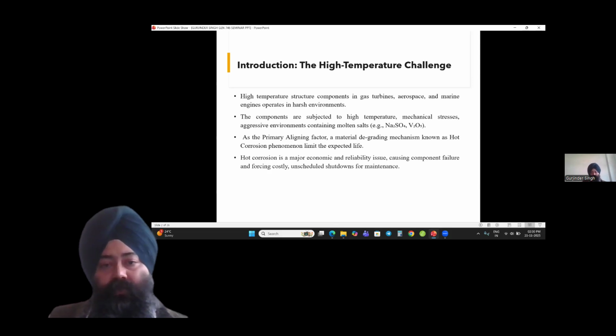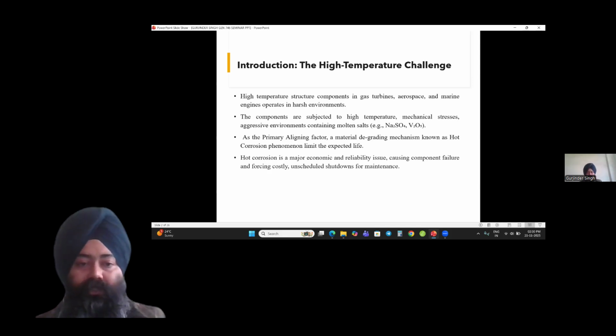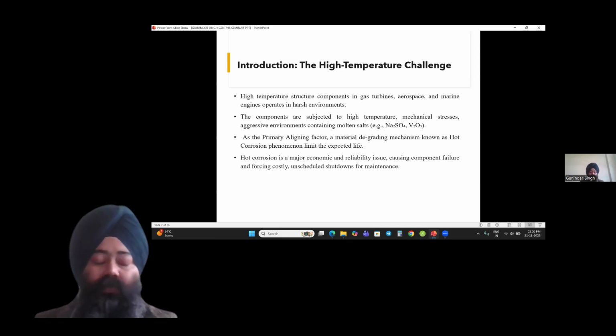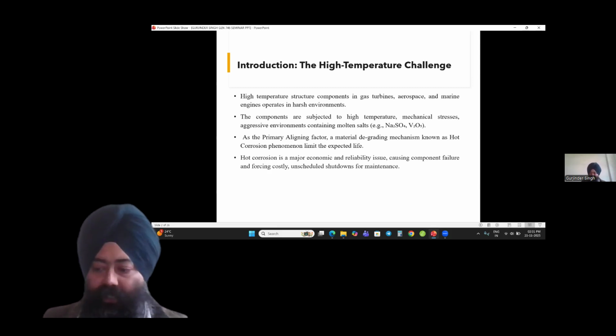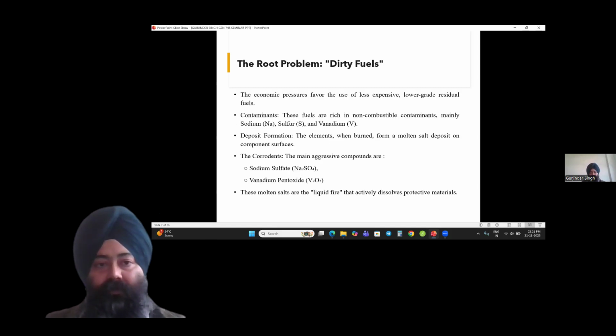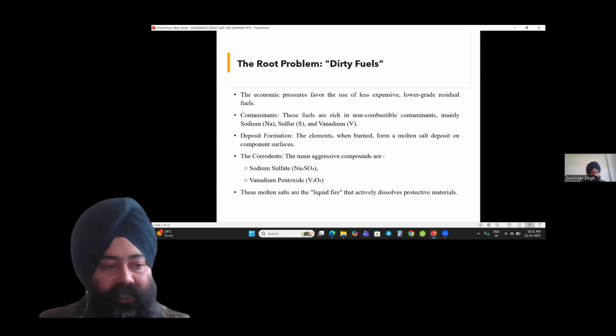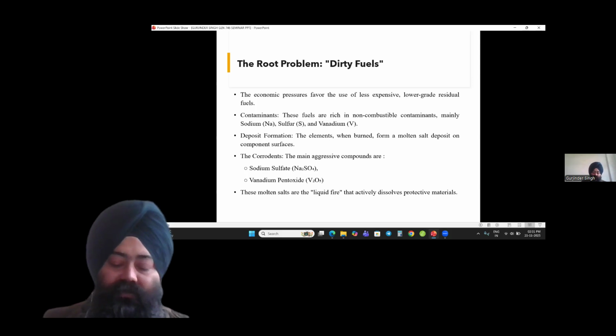due to our environment condition, there are some molten salt formations. And those molten salts are mainly sodium sulfate, Na2SO4, and vanadium oxide, V2O5. And these molten salts have a major effect on our material life. And now, what is the root problem of this corrosion?